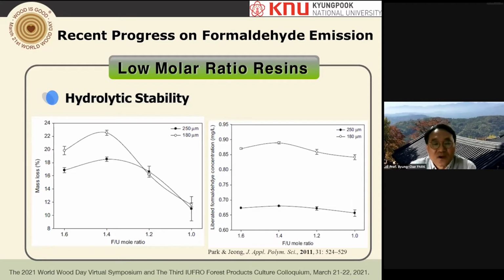And then we look at the hydrolytic stability. I mean, how these UF resins are hydrolyzed at the different molar ratios. So what we did is we prepared the different UF resins depending on molar ratios, and then cured them and ground them into powder, and then we have different particle sizes, and then put them in hydrochloric acid for artificial hydrolysis, and then we measure mass loss and liberated formaldehyde concentration after the hydrolysis.